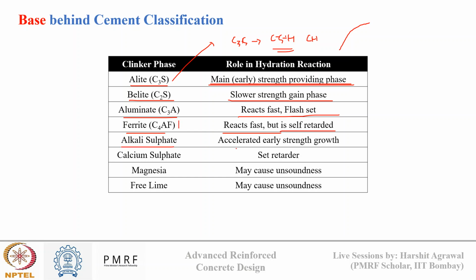There are alkali sulfates which can accelerate the early strength growth. There are calcium sulfates, which is gypsum, which act as a set retarder. So we saw aluminates, if they cause flash setting and we add gypsum, it converts aluminates into ettringite, which delays the setting. Then there's magnesia, which can cause soundness problem, and free lime, which can also cause soundness problem.